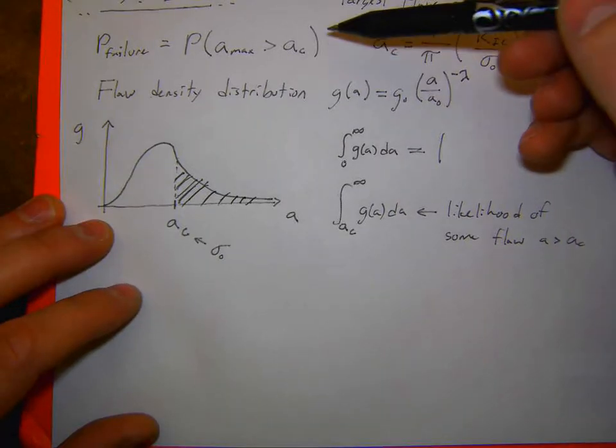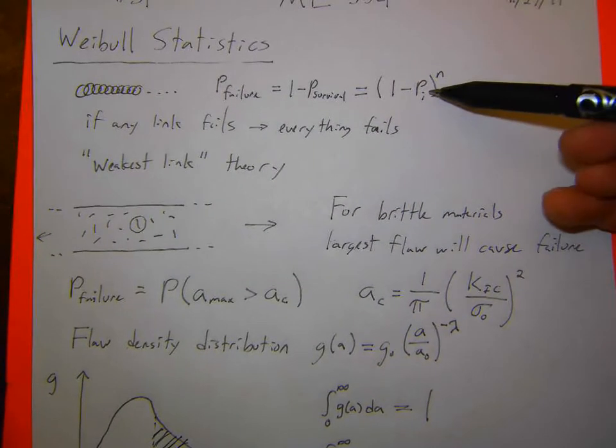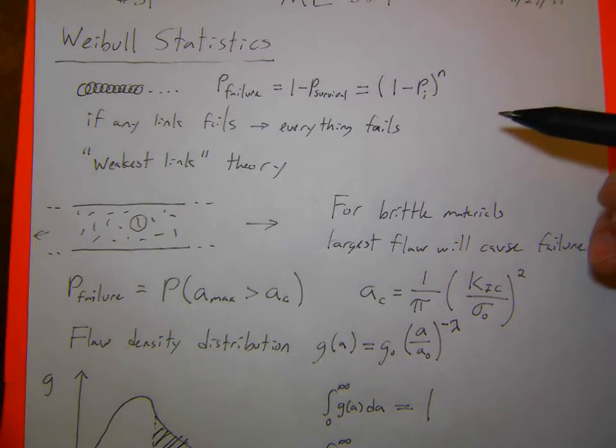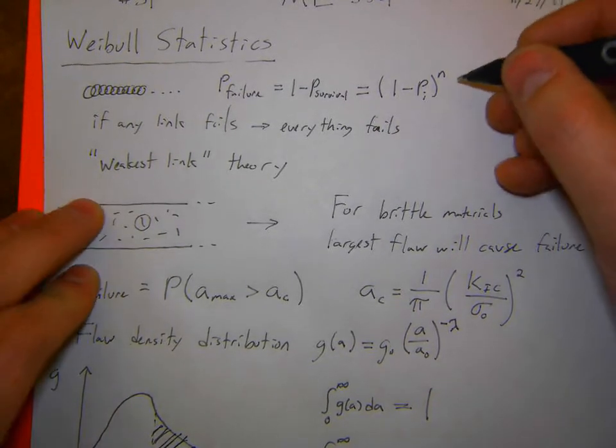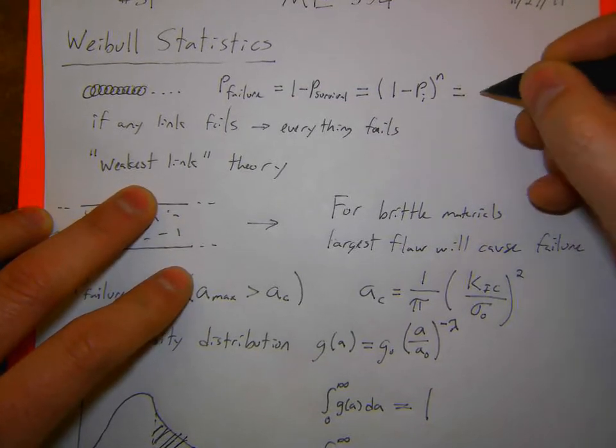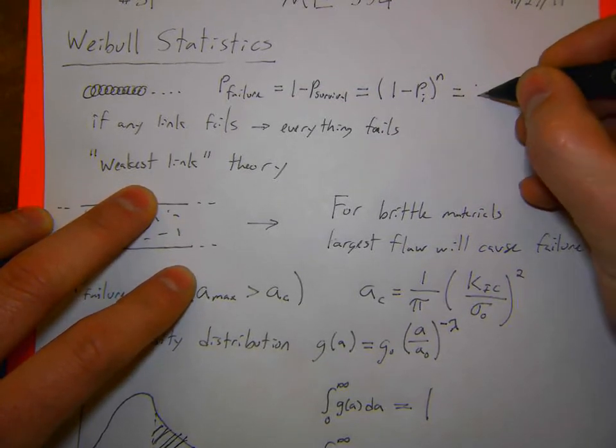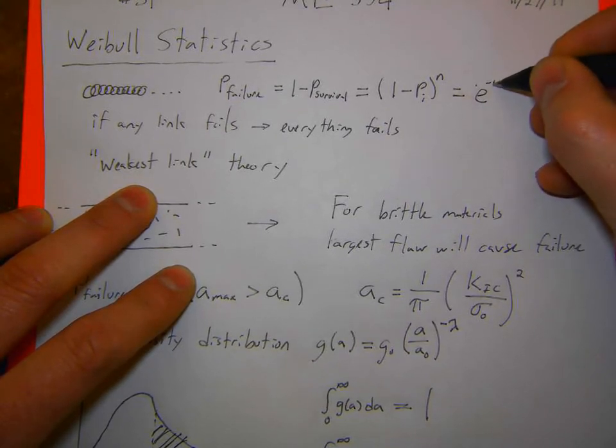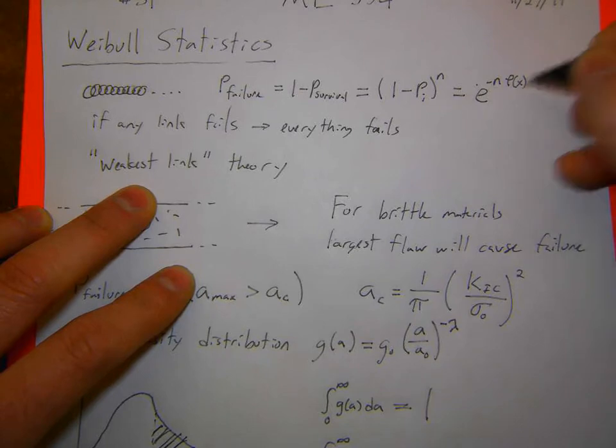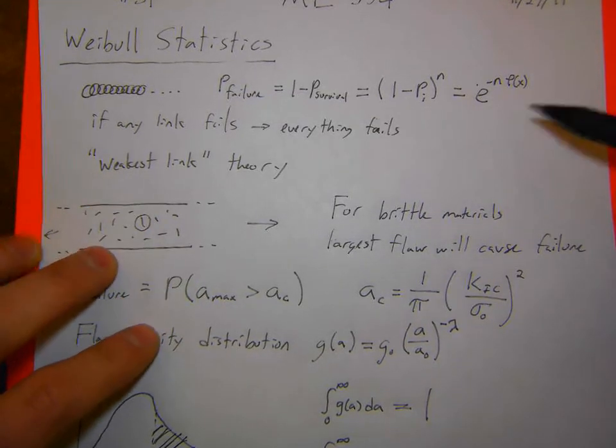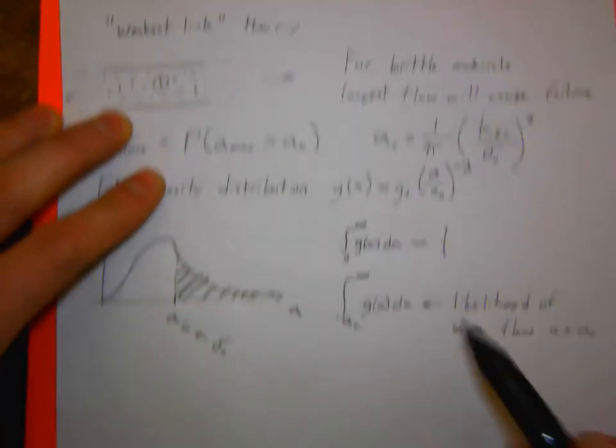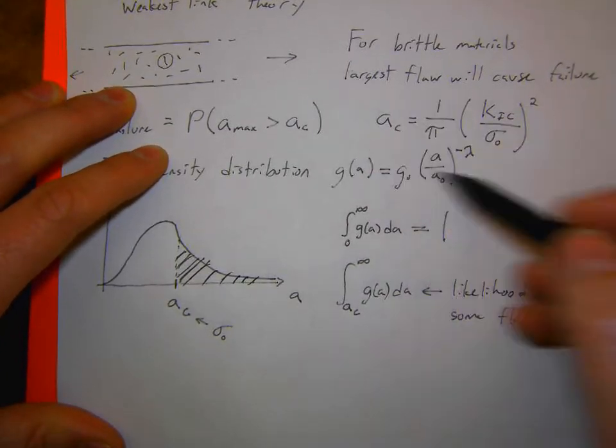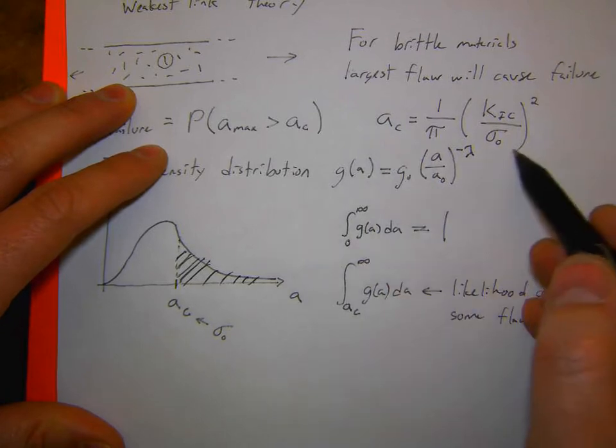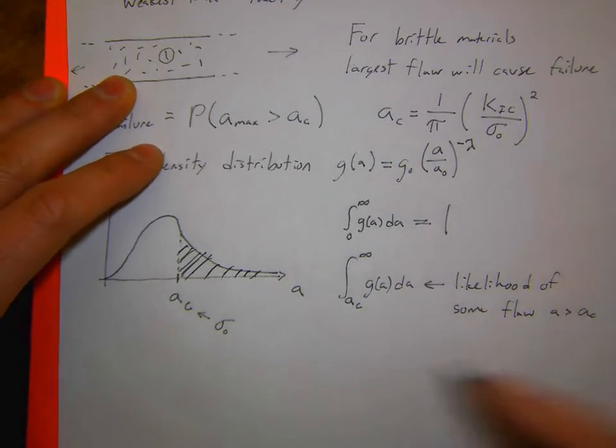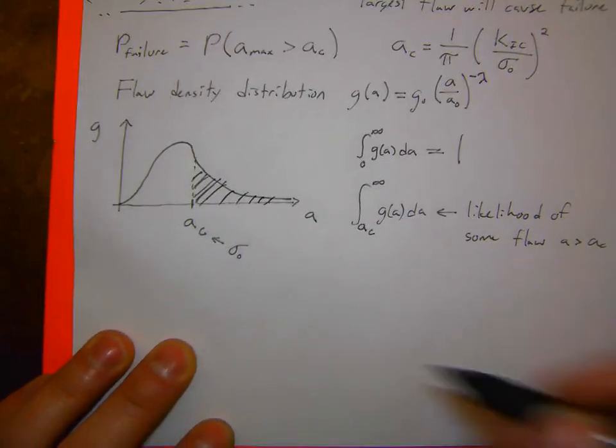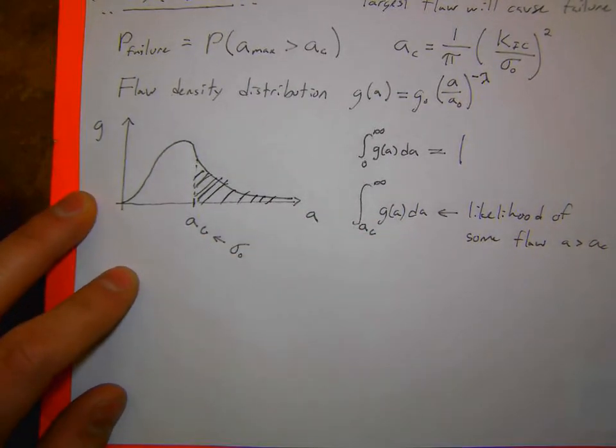So what we do now is we can take this idea of a flaw size, use some ideas from statistics, and say that this is actually equivalent to some e to the minus n phi. So this is related to some exponential function. I use that exponential relationship, this distribution of flaws, the relation between my critical flaw size and fracture strength. I combine them all, take a couple integrals, and what I end up with is the probability of failure in a material.